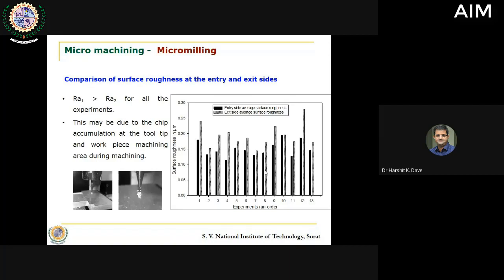And the other observation was that the roughness was greater at the entry. So RA1 was more than RA2 for all experiments. That is observed, and that may be because the chips would accumulate at the tool tip and would also resist the actual machining being carried out. Sometimes we observed that tiny particles would adhere to it. So there was a built-up edge formation also to a larger extent, and the aluminum material would stick to the tool, and then you will have to clean it. And in the meantime, it might get slightly blunt and might result in poor quality of machining at a later stage.